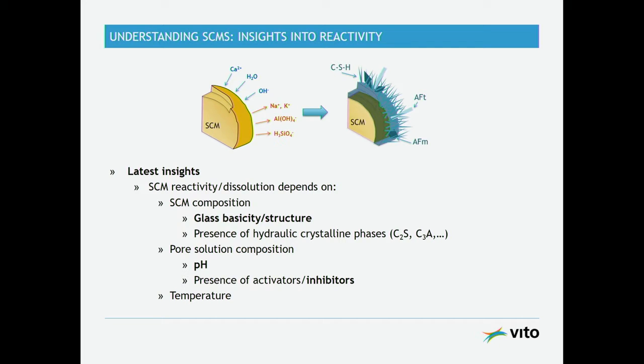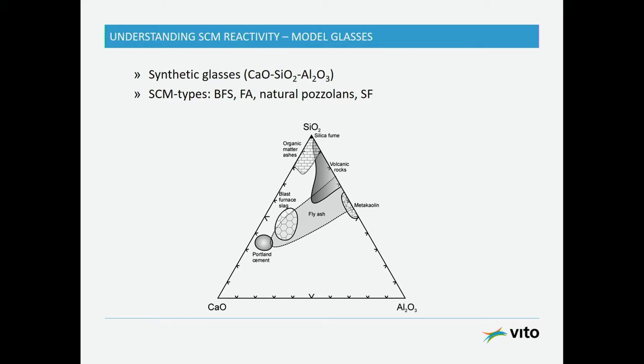Especially this latter part has not always been very much addressed when we are working in blended cement systems, for instance. So for now, I will show some results on how composition, pH, and inhibitors may actually affect the dissolution rates of your SCM. To take a step back, we simplified the system. So instead of looking at very heterogeneous SCMs, we synthesized glasses in the calcium, silicon, aluminum system. And they were chosen to compare well to, for instance, blast furnace slags, to fly ash, to natural pozzolans, up to a silica fume. So to remember, the lowest one, the G1, is the most calcium-rich one, and the G6 is the most silica-rich one.